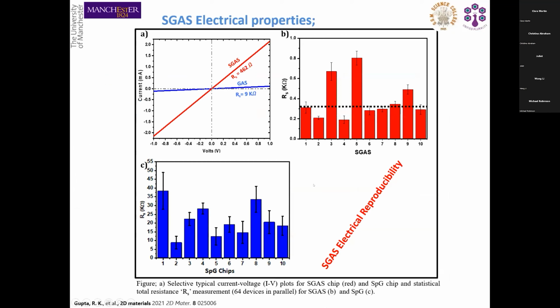And when we have graphene suspended and supported, suspended graphene will have reproducibility from batch to batch and in the number of devices when you move from one batch to another. So this is very good news in terms of going for large scale device fabrication. Otherwise, when we work with graphene, there's always the possibility that one device will be different from the other device, which can easily be seen with graphene on a supported substrate.